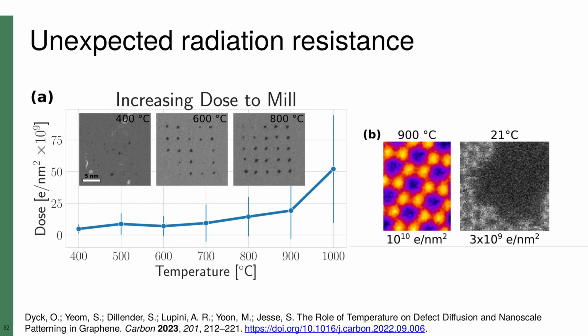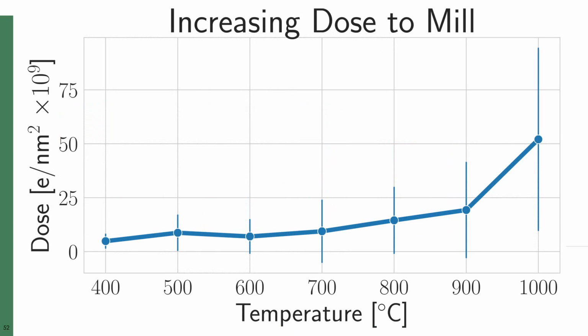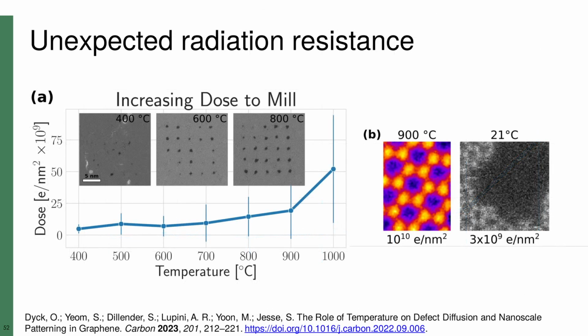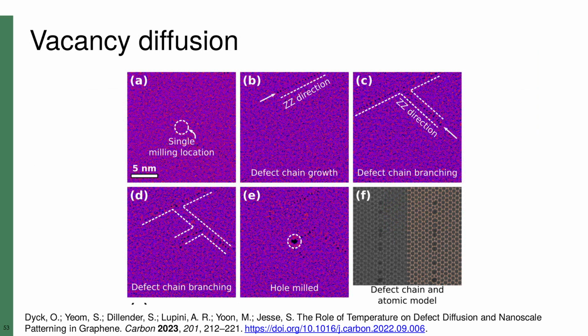This means that if healing is indeed playing a role, it is counteracting this trend. In other words, if healing did not happen at all, this trend would be more pronounced, not less. Now this was quite a puzzle, and we were baffled for some time until we performed this experiment.